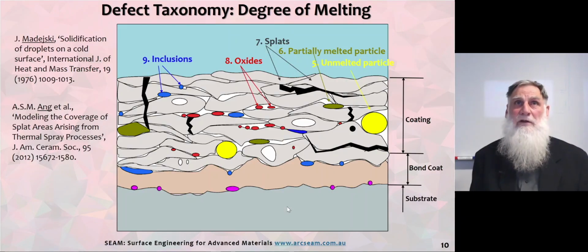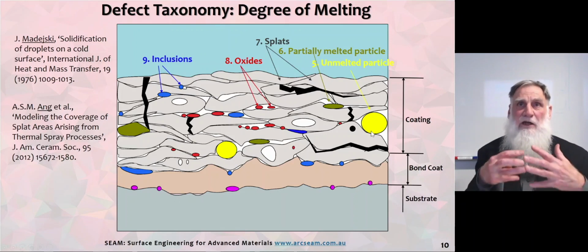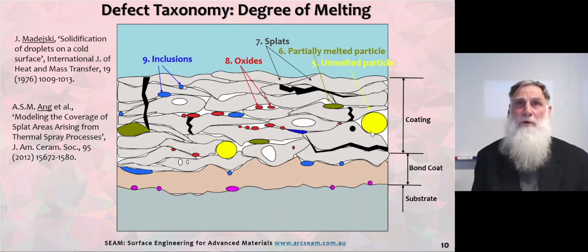So the defect taxonomy depends on the degree of melting, and some of the key work was carried out by J. Madejski in 1976, and more recent work by Ang et al. What this cartoon demonstrates is that there are many features within a coating. So we have the substrate, we have a bond coat, and then we have a splat structure of a ceramic overlay. And with the various colour renditions, we're able to see inclusions, oxide splats, partially melted particles and unmelted particles. And together, the composite of all of these defects gives rise to the ultimate properties. The point that I'm getting to is that if we can control these features, and if we can control the splat size, then we can change the nature of the coating and become very competitive with physical vapor deposited coatings.